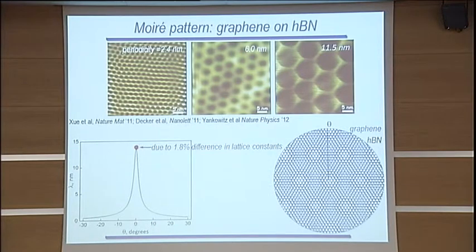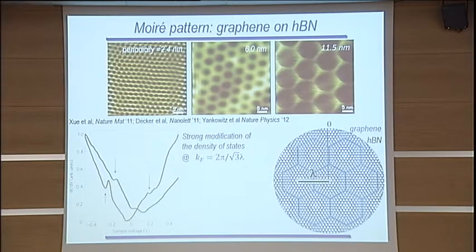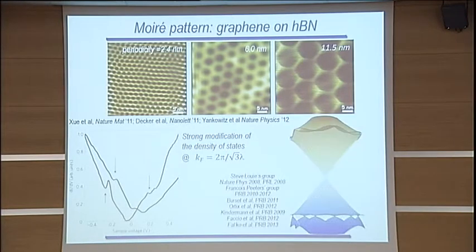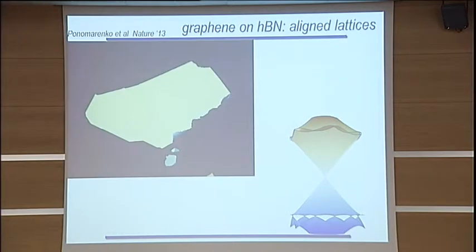I mean, the wavelengths are of course large, but the angles which allow you to see it are only plus minus 2 degrees of the misorientation between the two lattices. So if you leave it completely to chance, you would be very unlikely to observe this effect at all. So in that respect, what we've done is we're very careful in our selection of the crystals which we use